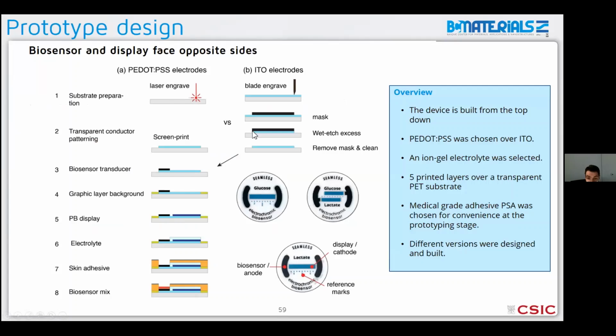So we thought about how to do this, and also there's a lot of work on the development of this electrolyte, but this is actually the fabrication plan. So in terms of the transparent electrode, we could use PEDOT:PSS, which is screen printable, or we could use indium tin oxide electrodes, which you can buy on PET with very high quality. But the problem for us was that if we used ITO, the process was a little more complicated because we had to etch the ITO from those areas where we didn't want it. And on the other hand, with the PEDOT, we just printed the electrodes, and that was the end of it. So we could streamline the process.